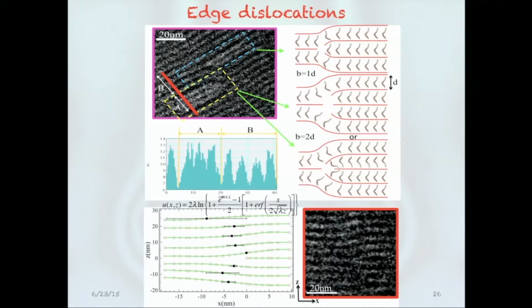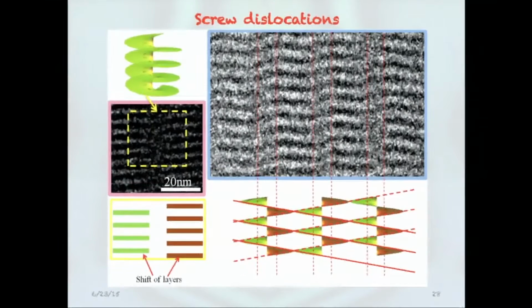On the other hand, we don't see this modulation, but we actually see lots of defects. And this was interesting for my colleague Oleg Lavrentovich, who is an expert on defects. And I used to tell him that my brain is full of bananas and bent-core something, and his brain is full of defects. But he's a very smart person. He's a world expert. And you could have seen his face was so happy to see defects in nanoscale, and then he could figure out what this periodicity is, and Burgers numbers and so on. You can do some nice theory. You can even see a tilt grain boundary phase. You can see screw dislocations. All these things are there, and you can see them with TEM.